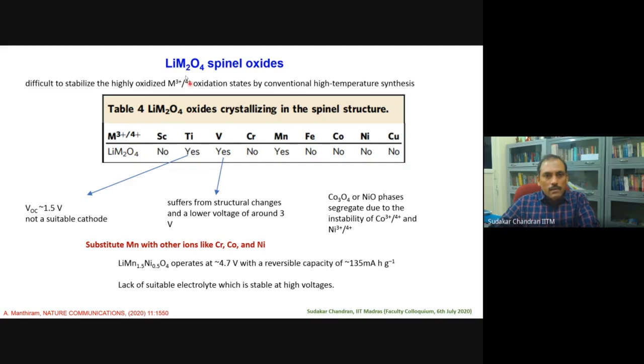Of course, in the LiM2O4 structure, many other spinel compounds were explored. Titanium has a spinel oxide, but then again, its voltage is very low because of where the titanium 3D levels position themselves in the band structure. Vanadium undergoes structural change. The cobalt and nickel oxides are very unstable in the higher oxidation state. Therefore, the only compound that could stay structurally stable is LiMn2O4.